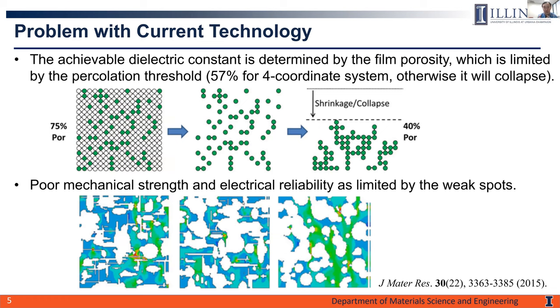Now, since air inside those nanopores have low dielectric constant of 1, it helps to reduce the effective dielectric constant of the whole material composite. Therefore, the achievable dielectric constant in this case is largely determined by the degree of the film porosity. So if we want to further reduce the K value from 2.45 down to below 2 as our target in this case, it means we need to further increase the film porosity.